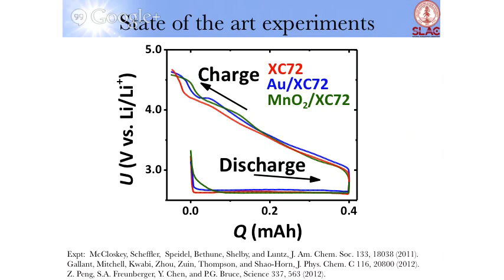And what is really interesting is that, so this is just carbon. This is gold on carbon, manganese dioxide on carbon. And beyond the initial nucleation phase, where you will definitely see some part of the catalyst, after that, the features are almost universal, independent of what catalyst you use. And so this, at least in a clean way, shows that the effect of catalyst is not important beyond the nucleation phase. So that means that what determines the thermodynamic efficiency of the cycle is essentially growing of lithium peroxide on the discharge cycle and the etching of lithium peroxide on the charging cycle.